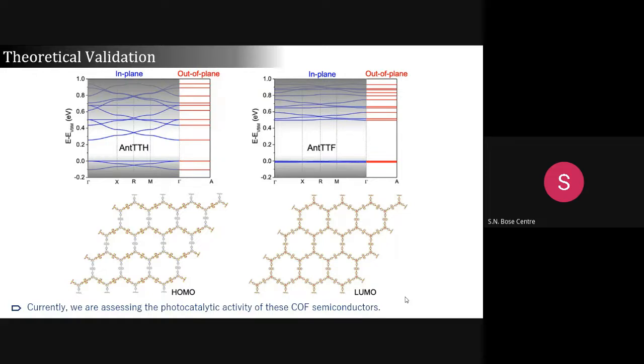Also, it is supported by the HOMO-LUMO calculation, where you can see that it is highly conjugated through this chain. And here is the calculation for the other one, which is non-planar. In the planar case, you can see large band dispersion, but in the non-planar case, the band dispersion is very slight. So that is why it has lower photoconductivity, and it has localized HOMO and LUMO. That is why we see very low photoconductivity in this one.